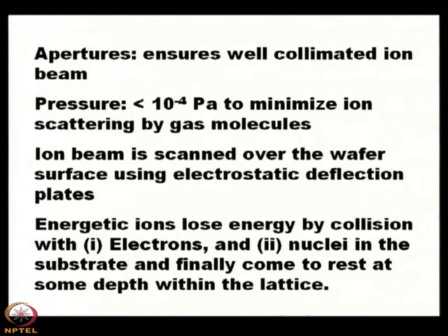And another important consideration is the pressure. The pressure inside the chamber, inside the accelerator, must be 10 to the power minus 4 Pascal. It is a very, very small pressure, to minimize ion scattering by gas molecules. Because